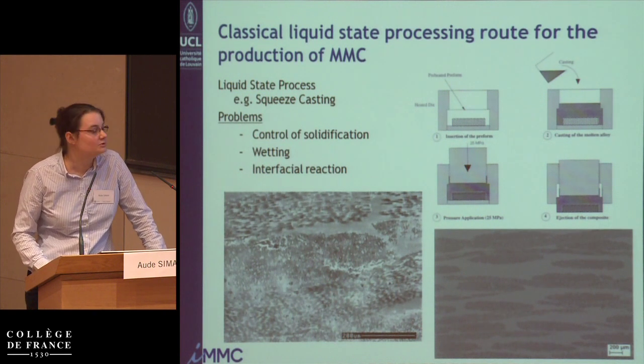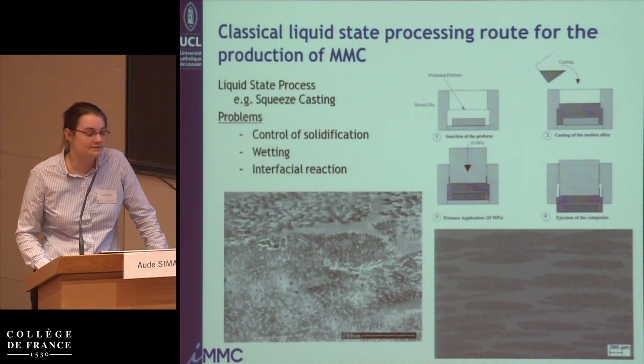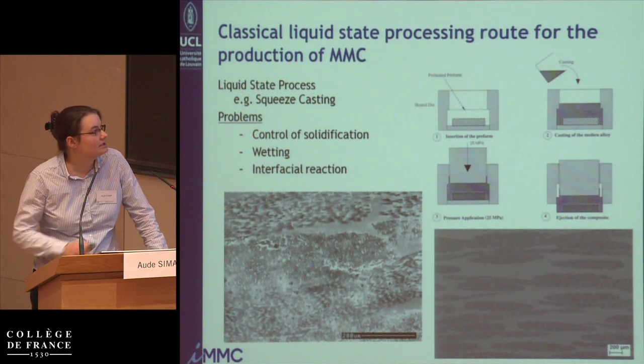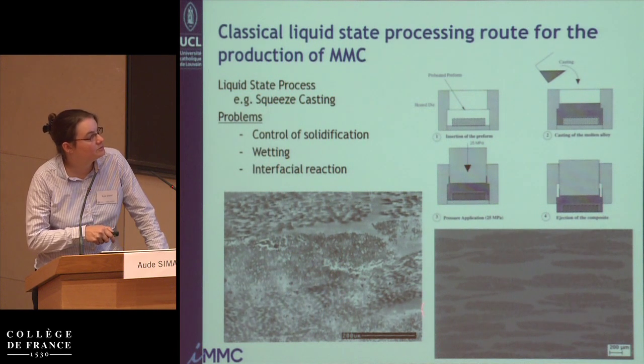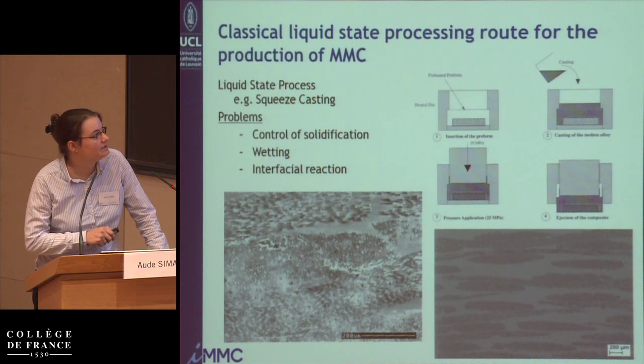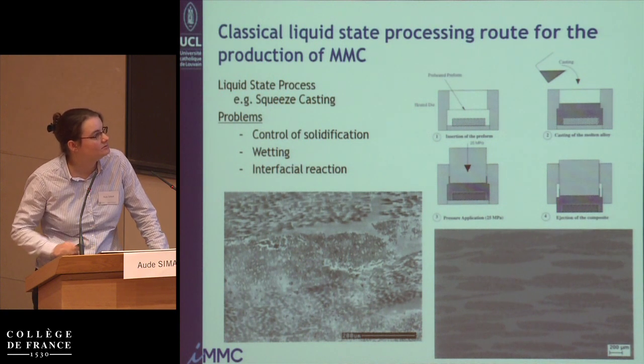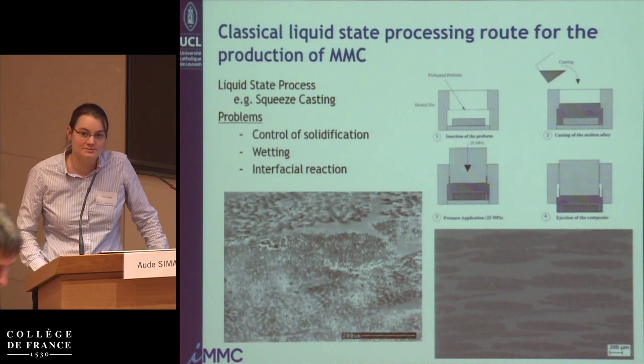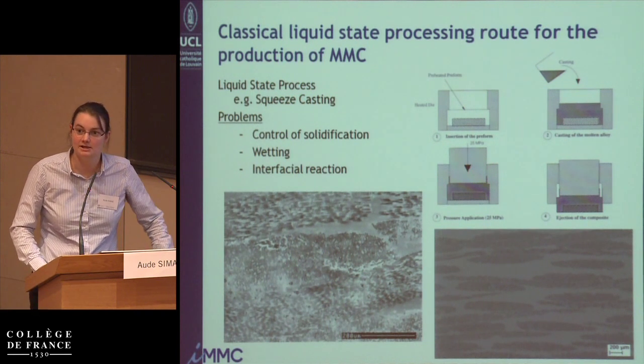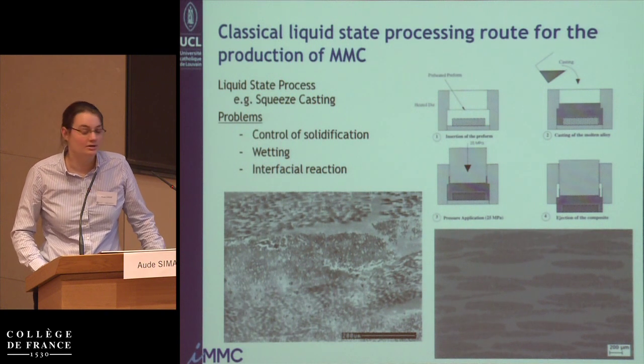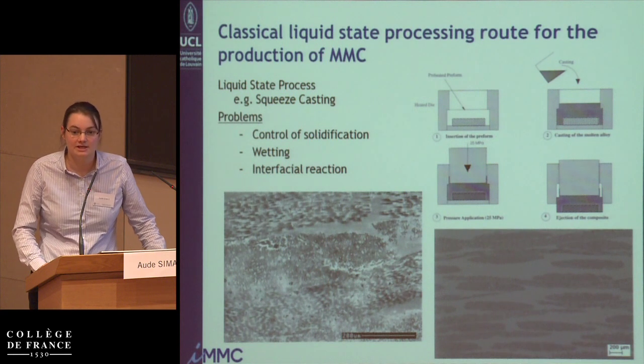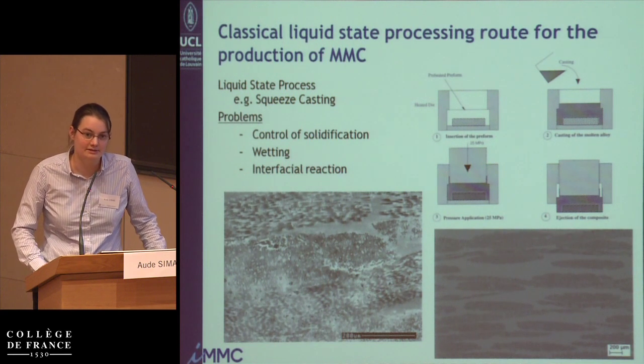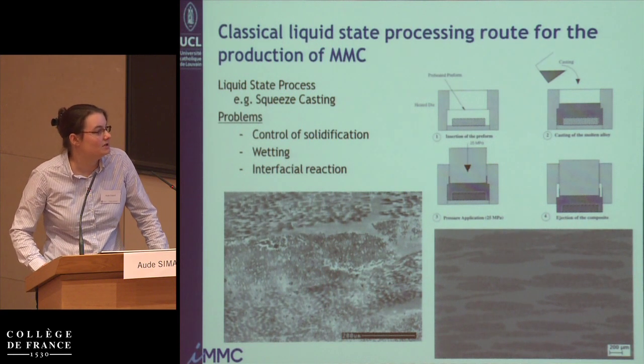It's very difficult to control these kinds of processes. In particular, before doing this, we made things like this. You have a lot of defects, problems of control of solidification, problems of wetting of the metal on the fibers, and interface reactions between the metal and the reinforcement.